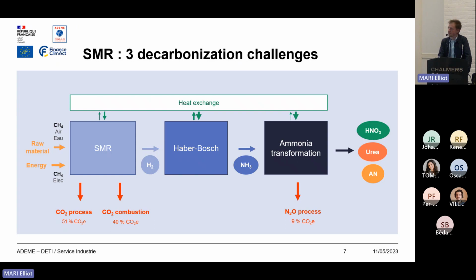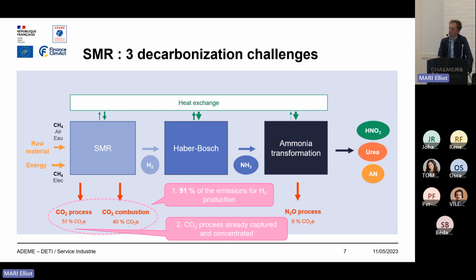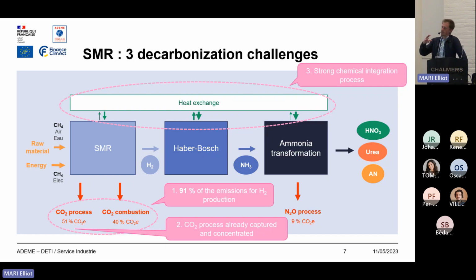Like every chemical process, they are heavily integrated. It means that if you change something on the steam methane reformer, there is an equilibrium that will be broken, or at least will change, between all the processes and all the equipment, because there is a lot of heat which is exchanged all around the site. So 91% of the emissions are concentrated on the production of hydrogen. These emissions are quite concentrated and the process CO2 is already captured. And here there is this heavily integrated heat exchange. That makes the decarbonization of an ammonia production site very difficult because of this equilibrium that will change.